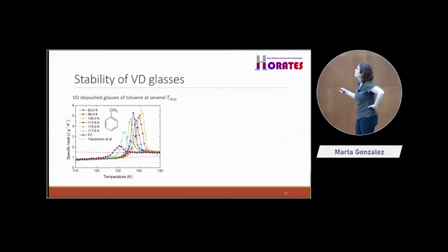This is the kind of measurements we are doing. This is a bit old, but still, this is toluene. These are vapor deposited glasses at different temperatures, and you see here specific heat curves, as I told you. And you see that at a certain temperature range, let's say this 104 Kelvin is like the optimum, the peak of the transition is shifted to the right. This is performed always in the same conditions, same heating rate, everything. The only thing that changes is that we are preparing the sample at a different temperature. So you see that the peak is shifted to the right, so that means it's more kinetically stable.